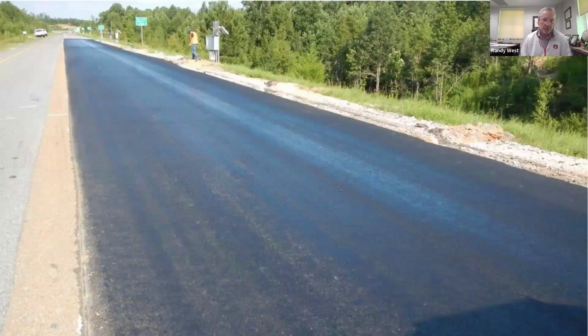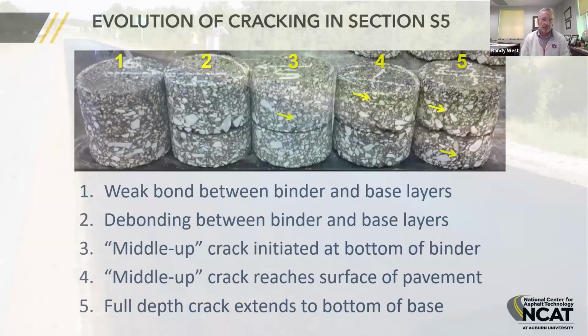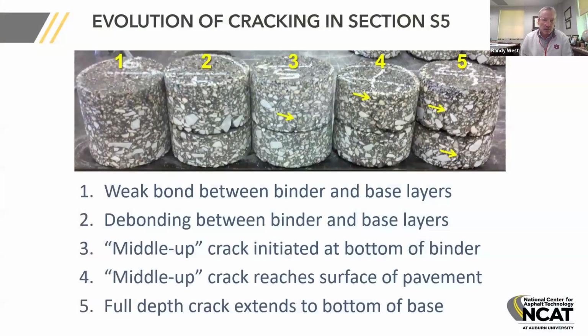And we went back and looked at pictures of the tack coat that we had during construction, and it's actually a pretty decent application of tack. A little bit rich, kind of in the right wheel path, but not too bad. Anyway, it wasn't like, oh, there's something wrong with what we did for the application of the tack coat. But we ended up with premature failure of that section.